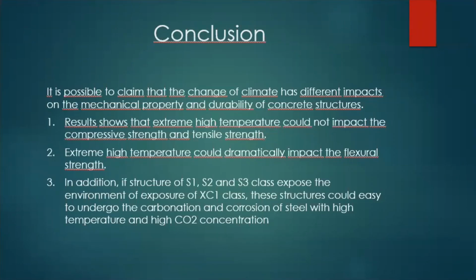Conclusion: it's possible to claim that the change of climate has different impacts on the mechanical property and durability of concrete structures. Results show that extreme high temperature could not impact the compressive strength and tensile strength. Extreme high temperature could dramatically impact the flexural strength. In addition, if structures of S1, S2, and S3 class are exposed to an environment of exposure class XC1, these structures could easily undergo the carbonation and corrosion of steel with high temperature and high carbon dioxide concentration.